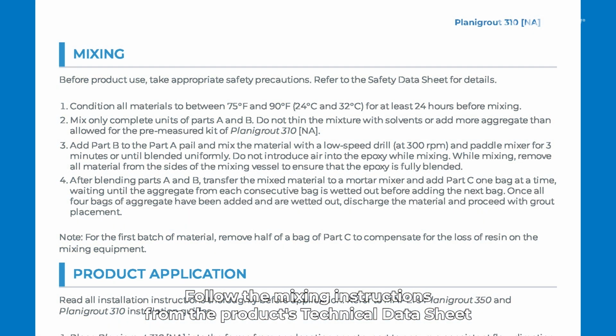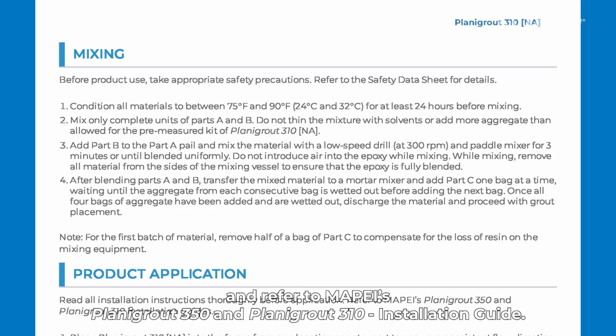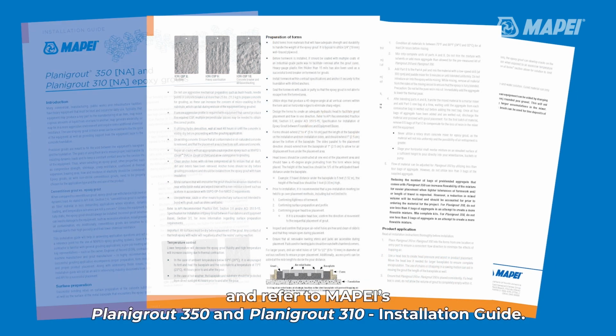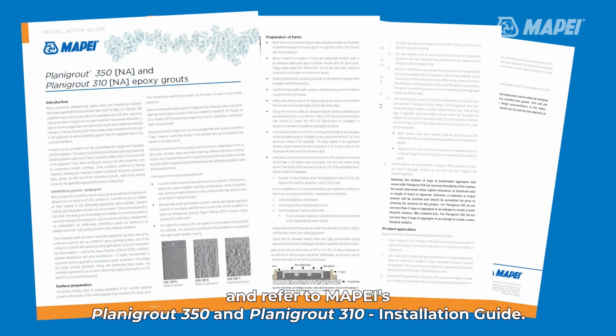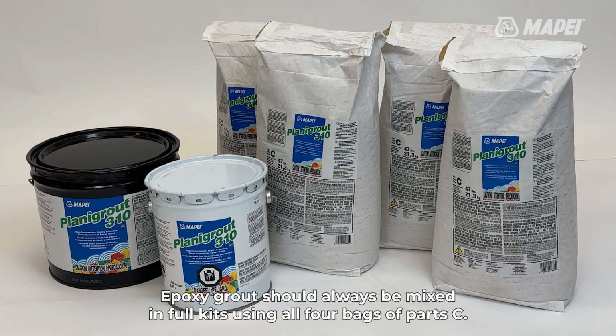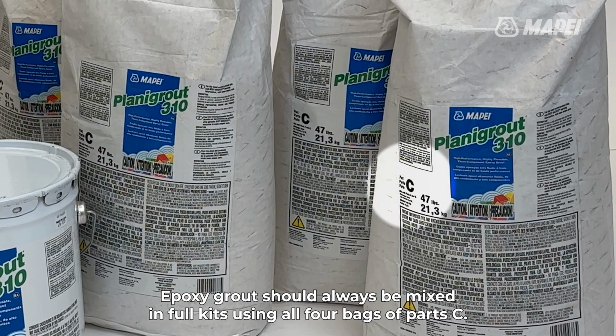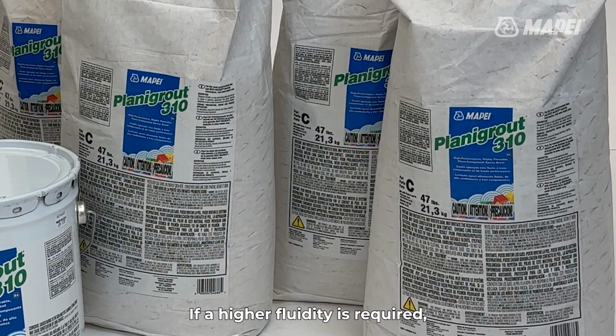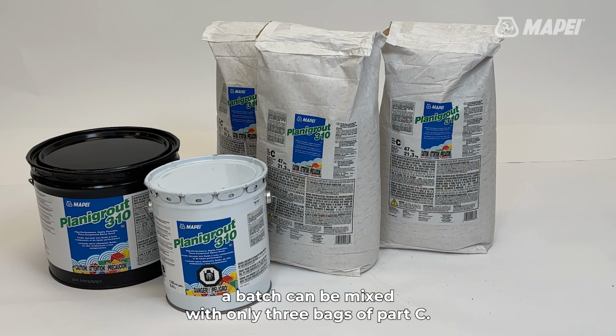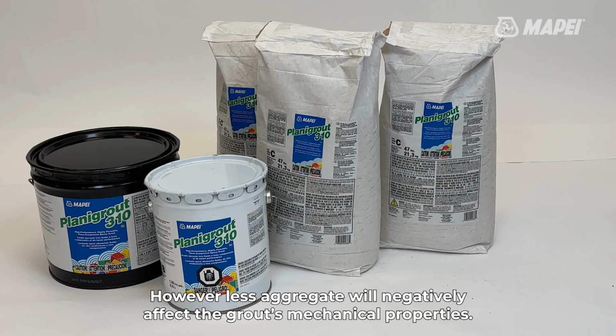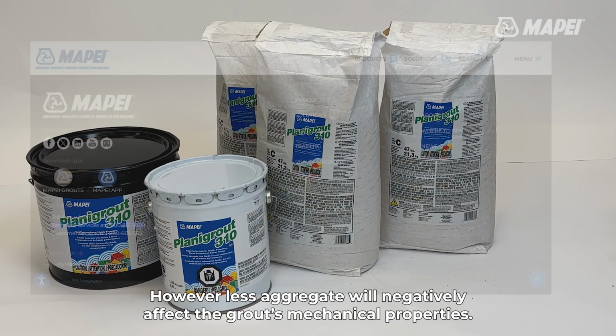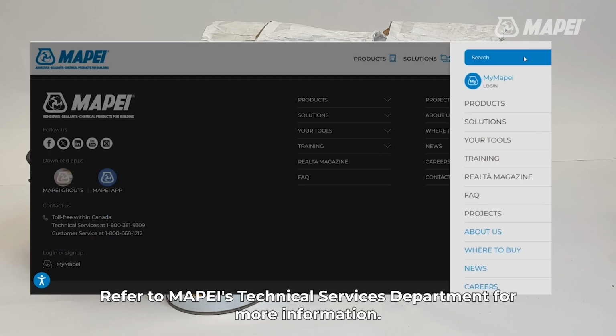Follow the mixing instructions from the product's technical data sheet and refer to MAPEI's Planigrout 350 and Planigrout 310 installation guide. Epoxy grout should always be mixed in full kits, using all 4 bags of Part C. If a higher fluidity is required, a batch can be mixed with only 3 bags of Part C. However, less aggregate will negatively affect the grout's mechanical properties. Refer to MAPEI's Technical Services Department for more information.